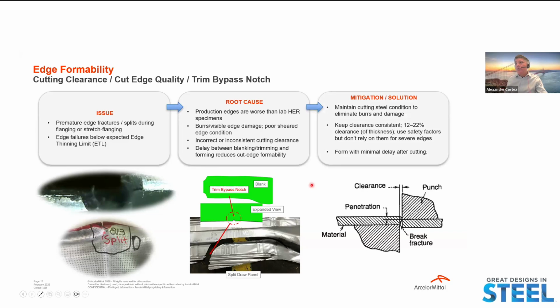As a mitigation solution, maintain cutting steel conditions to eliminate burrs and damage. Keep clearance consistent between 12 to 22% of thickness. Use safety factors, but don't rely on them for severe edges, and form with minimal delay after cutting.